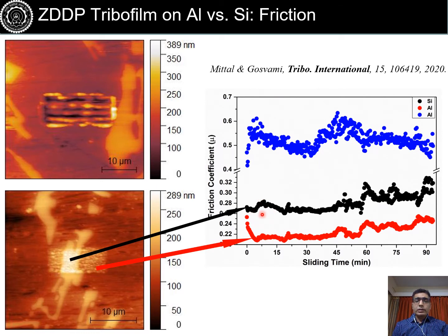Of course, it's higher on silicon, and we believe that higher friction on silicon is because ZDDP film increases friction, and this film is quite thick on silicon compared to aluminum, so that results in higher friction on silicon, whereas in the beginning there was not that much of difference, but as the film thickens there is more friction on silicon due to thicker tribofilm, whereas friction coefficient shoots up quite strongly when there is wear of aluminum matrix. So very nicely we can see that as soon as wear starts, how friction coefficient becomes very large, and very locally we can study these differences by using an AFM.